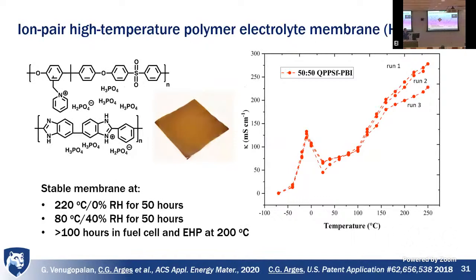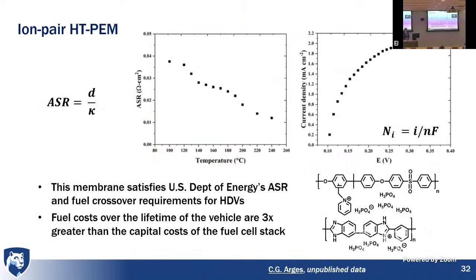So I think in the interest of time, I'm going to skip over this really fast. We have a very good membrane, conducts under wide temperature. We sell this commercially, stable for conditions. And furthermore, it hits Department of Energy's heavy duty vehicle truck applications in terms of the area specific resistance, that's the thickness of the membrane over conductivity. You don't want just high conductivity. This is what you want. And at high temperatures, we can get under 20 milliohms per centimeter squared.